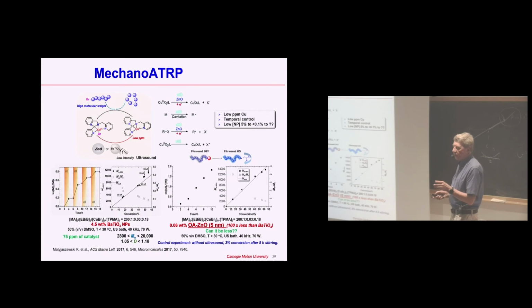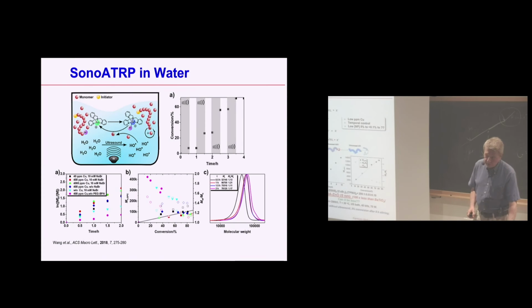If you switch from barium titanate, which was the original work, to zinc oxide, we now work with zinc oxide of only 5 nanometers, stabilized by octylamine, and you can have a concentration of zinc oxide of 0.06 weight% in comparison with 5 weight% for barium titanate. So it works pretty nicely, and we wanted to extend it further, using lower and lower concentrations of zinc oxide. So we went from, let's say, 0.06 weight% to 0.01% to 0.001%. Eventually, in water, we went to 0, no zinc oxide, and the reaction was still working.